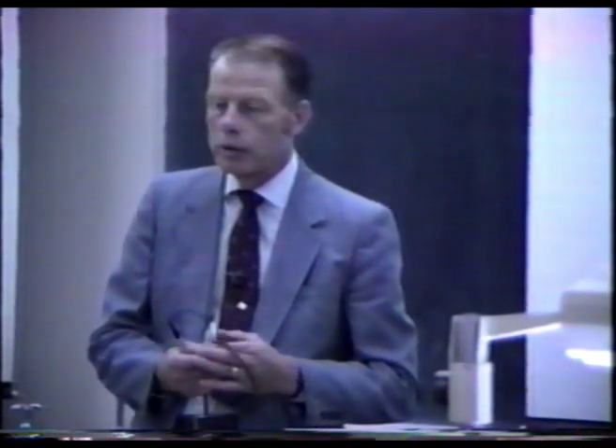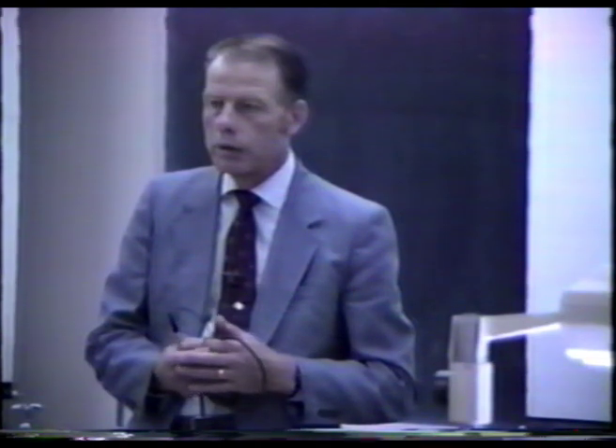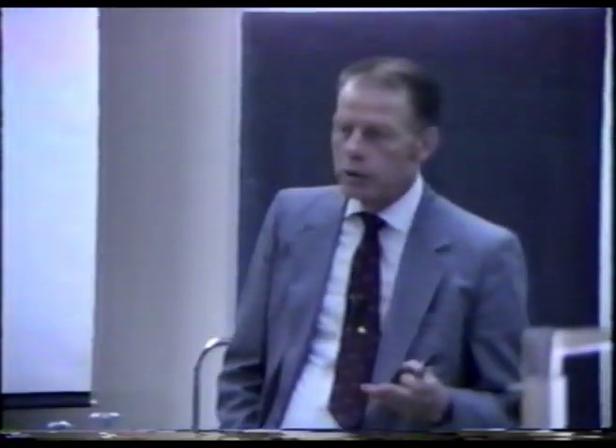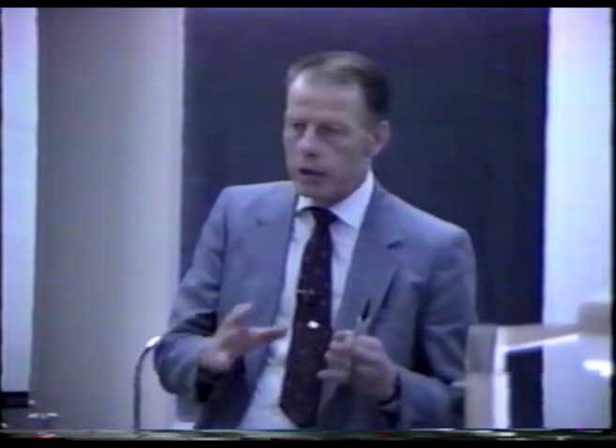Right. Any positive effect you've noticed? Yeah, it's H2O addition. In fact, Takahashi talked about this as well. He reports that when he adds H2O, the effect seems to diminish. Bockris has reported also for his tritium results that when he adds H2O, the tritium production seems to go down. If this is a surface effect, adding this H2O can greatly affect the surface.